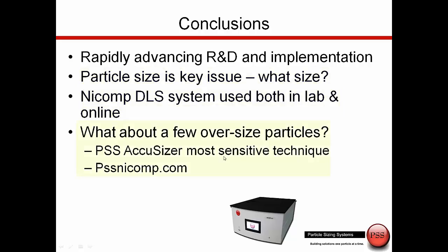Unfortunately what I couldn't show today is: what if there are a few oversized particles in the batch? How are you going to detect those? DLS isn't going to detect particles up at over 1 or 10 microns. The other technique available through PSS is the AccuSizer — a single particle optical sizing system where we count and size particles one at a time. It's the most sensitive technique for catching a few oversized particles. If you have concern for a few large particles, the PSS AccuSizer is our recommended technique. For more information, please visit our website at PSSNicomp.com.